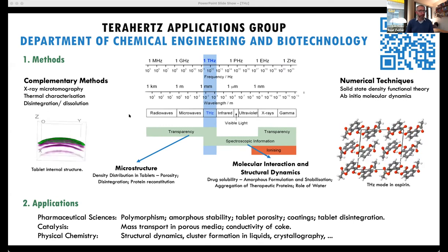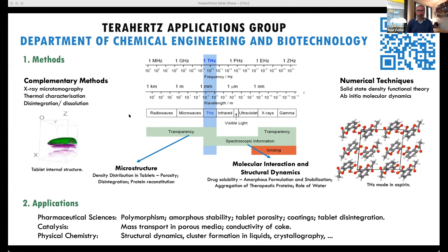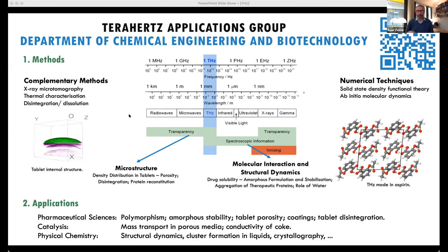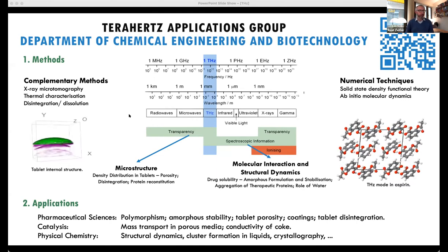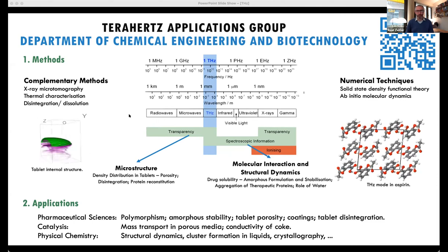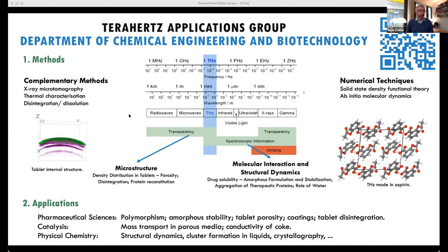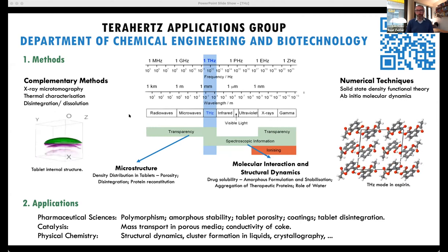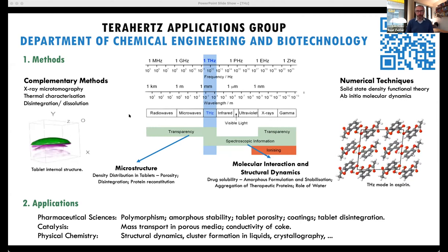And so this is terahertz radiation. We make this into a very short single cycle pulse. And then we can probe objects with that pulse and look at the reflection. And depending on how long the pulse takes to come back, we know how deep the structure originates from inside. So this is like a reflection tomography technique, essentially. And so now we can explore materials that are opaque at visible frequencies, but are transparent to terahertz frequencies. And like I said before, this could be polymers or ceramic structures.